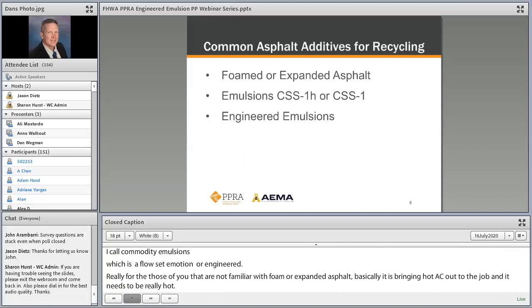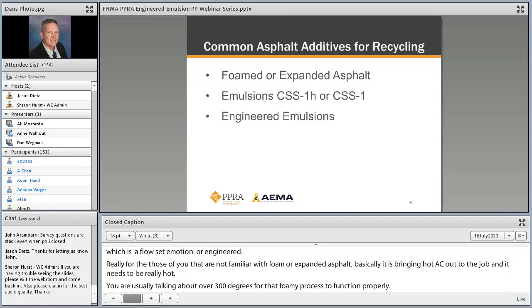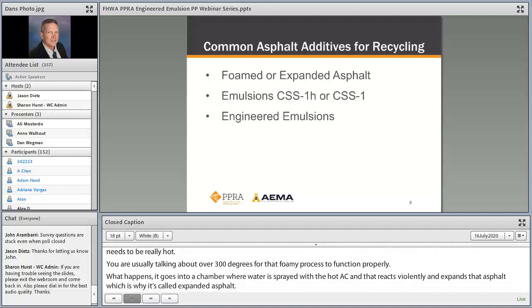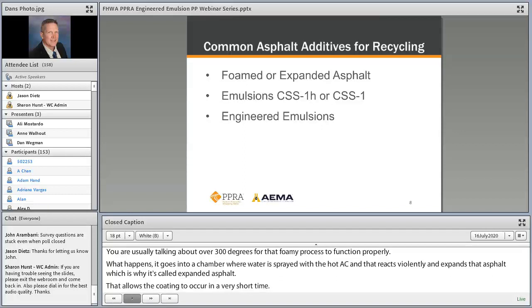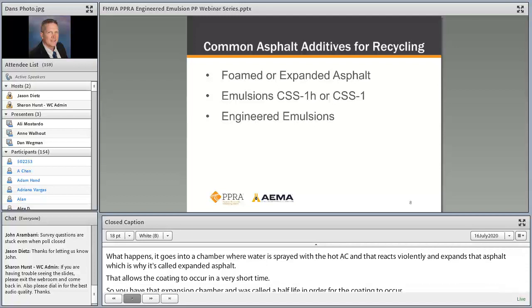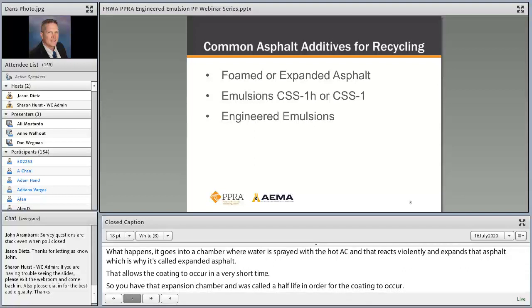And what happens is it goes into a chamber where water is sprayed with that hot AC, and that reacts violently and expands that asphalt, which is why it's called expanded asphalt, and that allows the coating to occur in a very short period of time. And so you've got that expansion chamber and what's called a half-life in order for that coating to occur. And so what happens is the fine aggregate in that base material gets coated, and a lot of people call it a spot weld, where those coated fine aggregate materials hold the coarse aggregate in place.